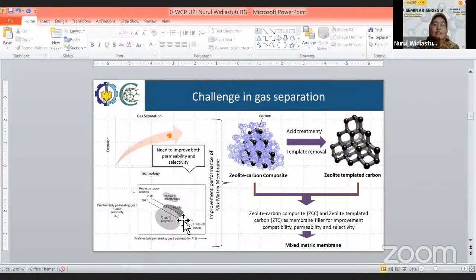As we see here, the Robeson upper bound for organic polymers is a bit lower than the trade-off curve, while the inorganic membranes are higher than the trade-off curve. And by combining both of the materials, called mixed matrix membranes, they will improve the performance of the organic membrane in order to achieve the trade-off curve of the Robeson upper bound here. So the challenge in mixed matrix membranes really depends on the polymer matrix itself, and also the filler that we will use for the mixed matrix membrane preparations.